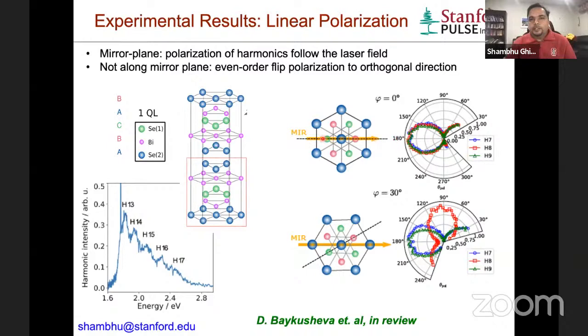Here is the polarization measurement when the laser field is along the mirror plane. There are three mirror planes. So here the laser field is along the mirror plane. In this condition, we see both even and odd order harmonics, all polarized along the laser field. But when you rotate the crystal and the polarization is now 30 degrees away, not along the mirror plane, then we not only produce a significant amount of even orders, but these even orders, like harmonic 8, have their polarization flipped and go towards the perpendicular direction compared to the laser field and the other odd harmonics.